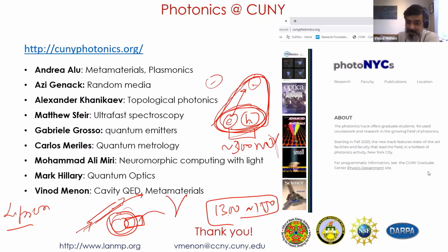So the only ones I can think of is the interlayer excitons, where the valley polarization should flip. But I should also point out that in second harmonic generation, it also flips the valley polarization, because now you have a 2-photon process that is creating this. And so when you emit, you emit with a circular handedness that is of the opposite polarization. So I'm not very familiar with the work that you're talking about, but definitely the interlayer has that property, and also the second harmonic signal shows this opposite valley polarization property.